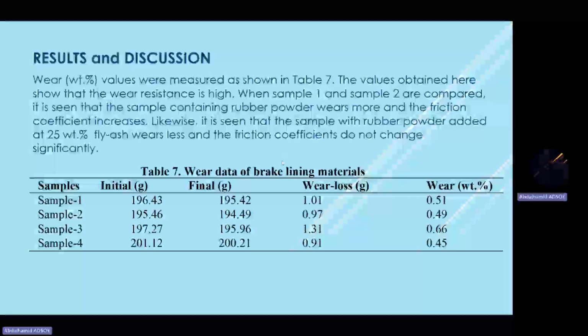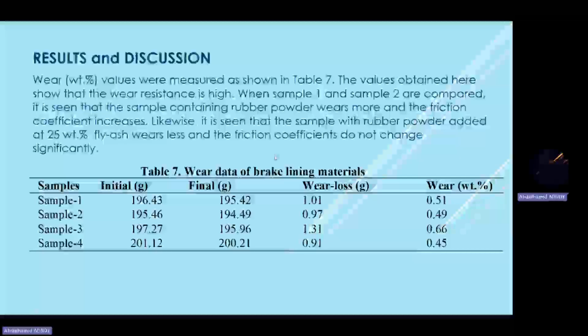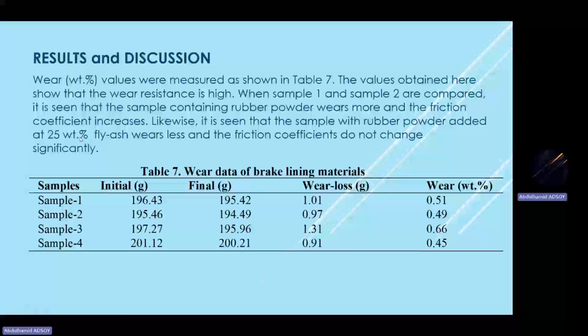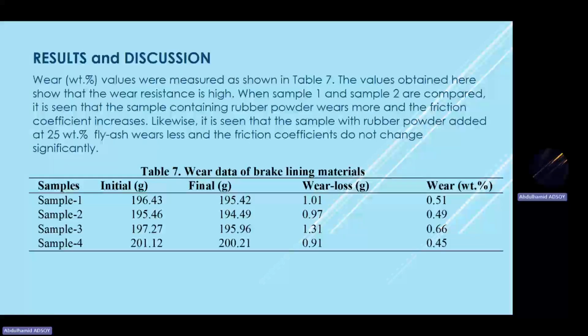Likewise, from the samples, we can see that the samples containing rubber powder at 25% by weight fly ash wear less, and the friction coefficients do not change significantly for samples 3 and 4.